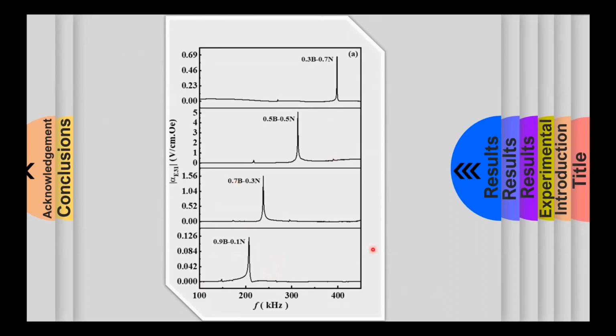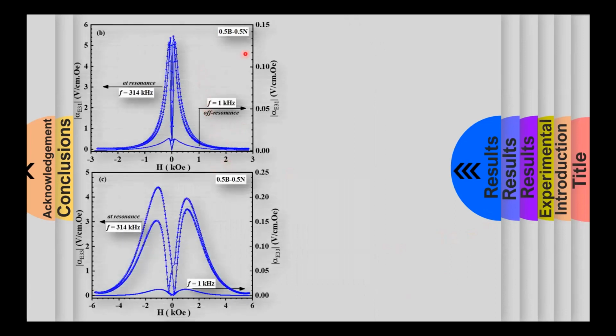But the notable observation in this was the substantial enhancement in the coupling response at resonance frequency. Here we take the example of the 50-50 composite. Here we see that there was a huge enhancement in the magnetoelectric response, both in the transverse mode as well as in the longitudinal mode. The value you see is around 5.5 volts per centimeter oersted, whereas in the off resonance condition, the maximum was 145 millivolt per centimeter oersted. Similarly, huge enhancement was seen in resonance mode in the longitudinal mode, and quite higher than the off resonance condition.